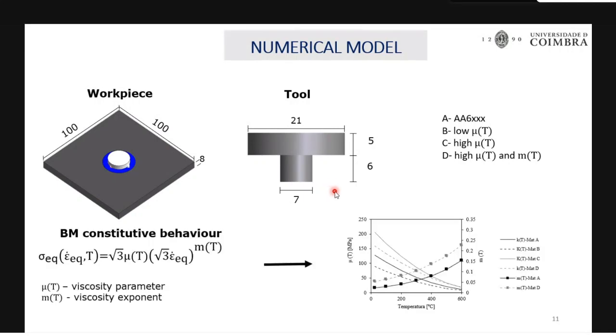And these are the dimensions of the workpiece and the tool which are used for the simulation. As I told in the previous slide, the main objective is to analyze the influence of material property. So what I am going to do is take AA6065 aluminum alloy, calculate the material parameter values, and multiply them. I'm using some multiplier of this viscosity exponent, for example 2, then 3, 4, 5. In this way, I just changed this viscosity exponent value. By doing this, I can analyze the influence of the material's plastic parameters.